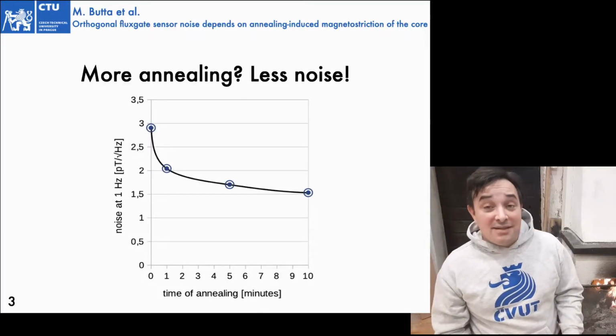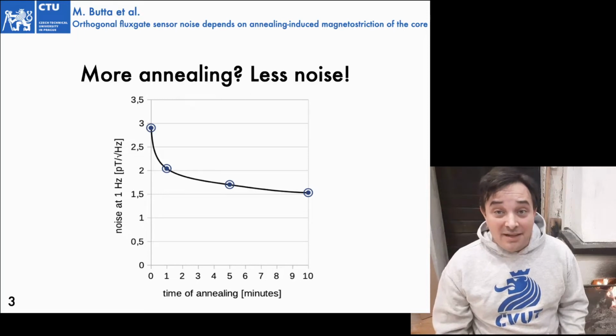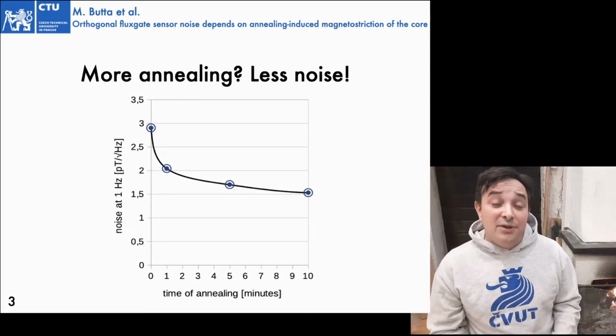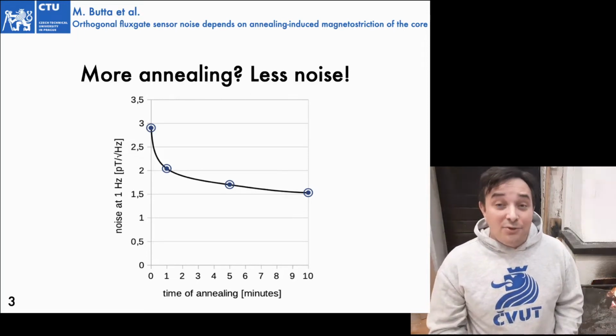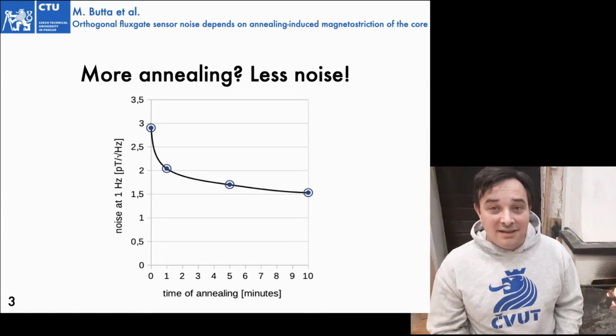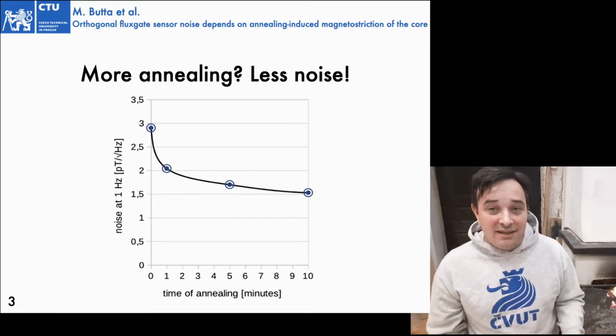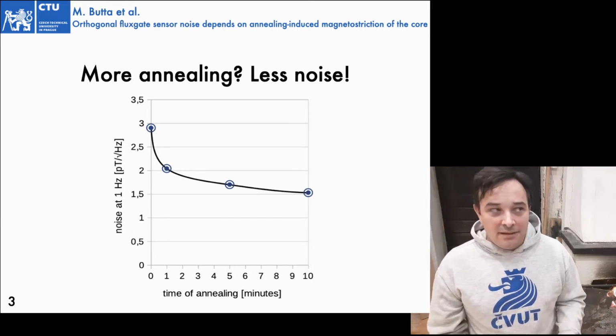This is actually true. In fact, you can see that the longer is the annealing time, the lower is the noise. In this graph, you can see the lowest possible noise that you can achieve using a single wire fluxgate with as-cast wire or with 1 minute, 5 minutes or 10 minutes annealing. As you see, the longer is the annealing, the lower is the noise. Then you might wonder, why don't you anneal it for a longer time? Why don't you anneal it for half an hour, for 1 hour? Well, the longer is the annealing, the lower is the noise, right?